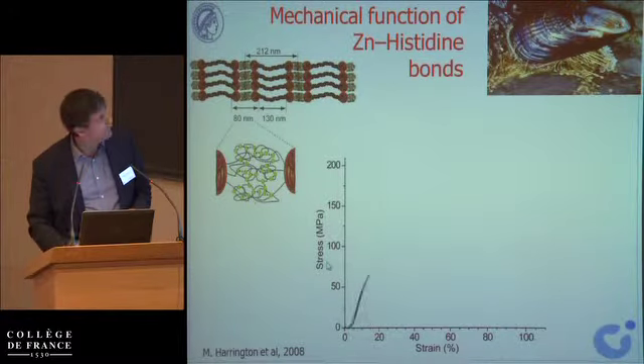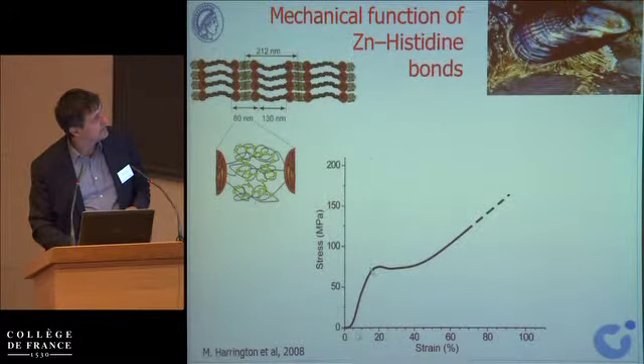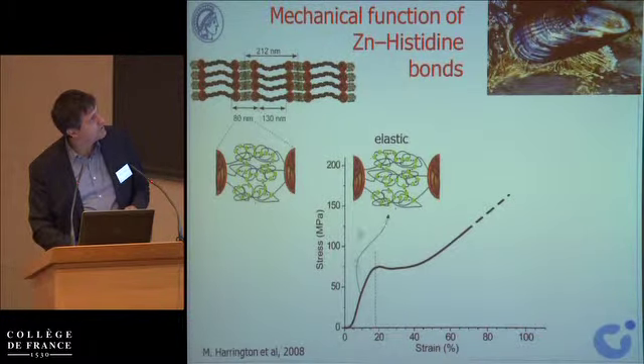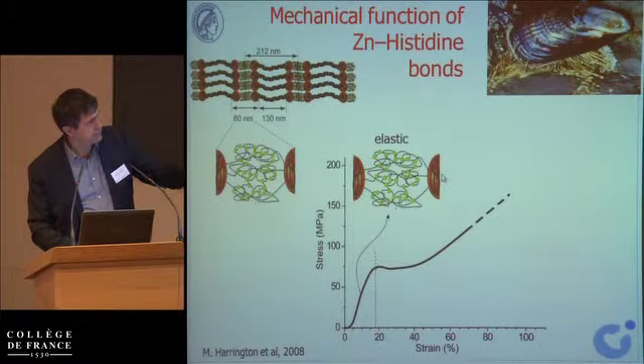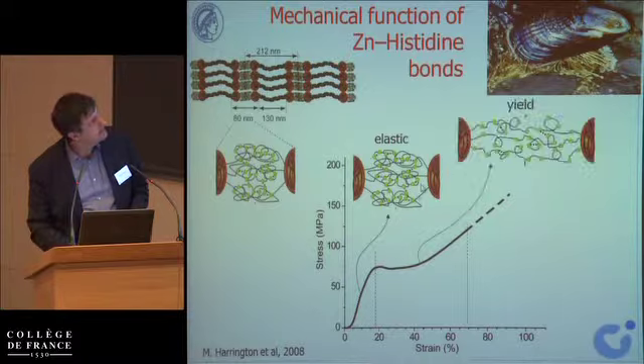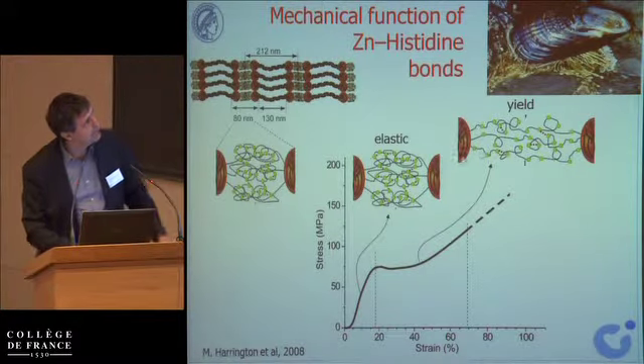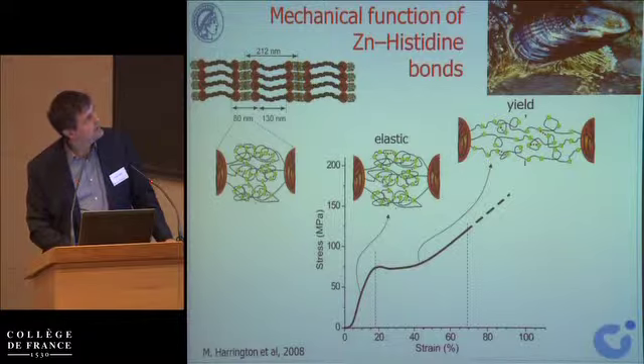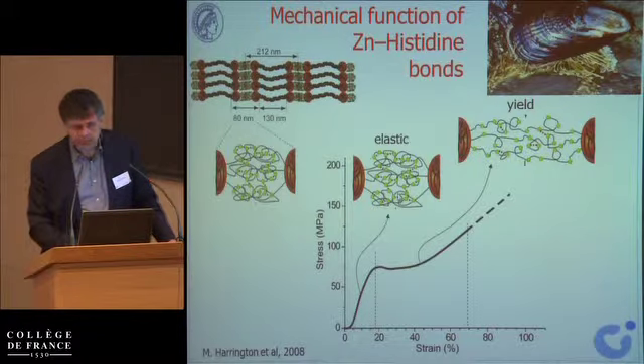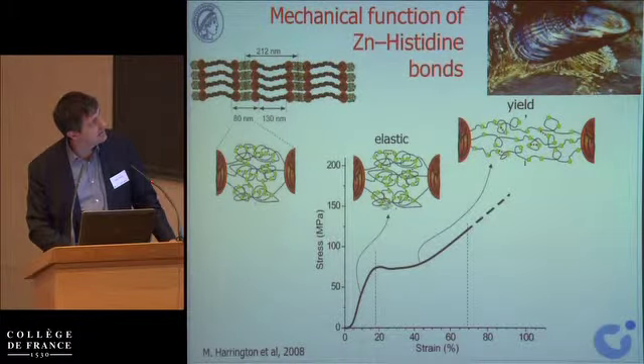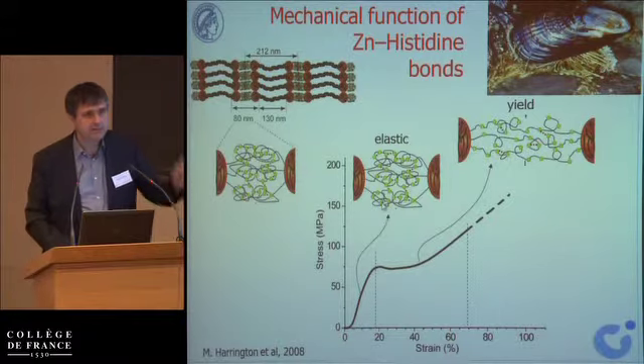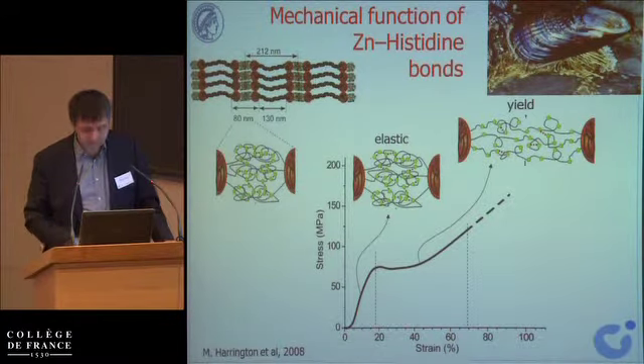and now we're going to pull. Here is the stress-strain curve, stiff in the beginning, large deformation. So in the beginning you start to pull on these folded domains here. The connector doesn't deform very much, it's just a very stiff connector, but this thing here changes, and you see now it starts to unfold. And what these little red bonds are, these are zinc-histidine bonds. Histidine is an amino acid that is able to be cross-linked to another amino acid by a metallic ion, which in this case is zinc.